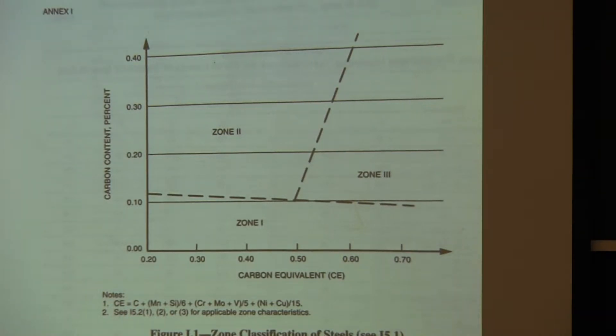Tolerate 30 ppm hydrogen, all kinds of things. Zone two is over here, this is some of your higher strength quenched and tempered steel. HY80 submarine steel is kind of right over here near this line but it's in zone two. 4340, oh no, this stuff is a real pain. Zone three, you're going to be getting up to this five and six hundred degree Fahrenheit pre-heat temperatures.